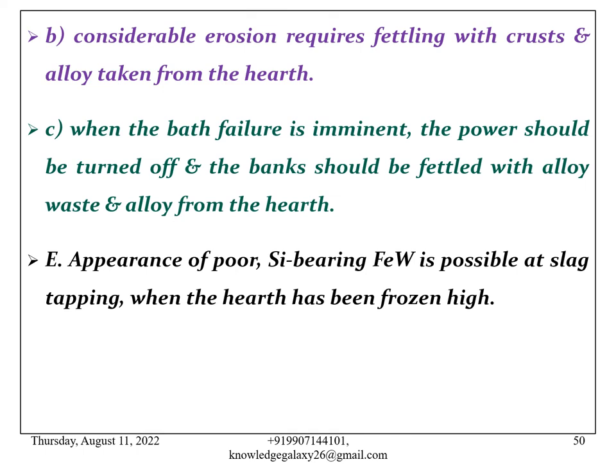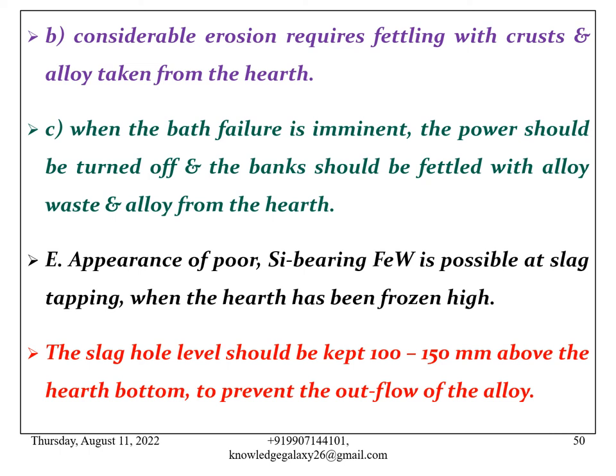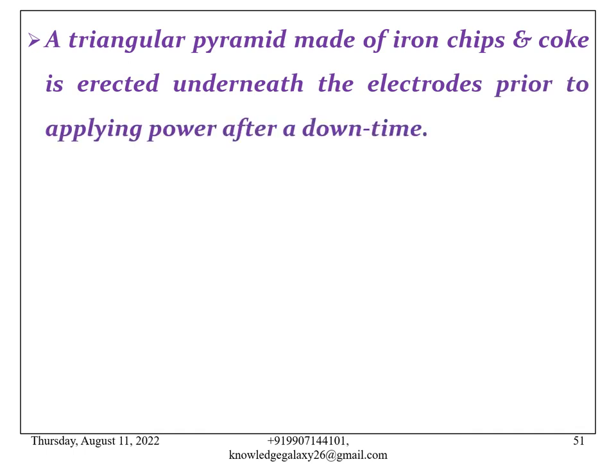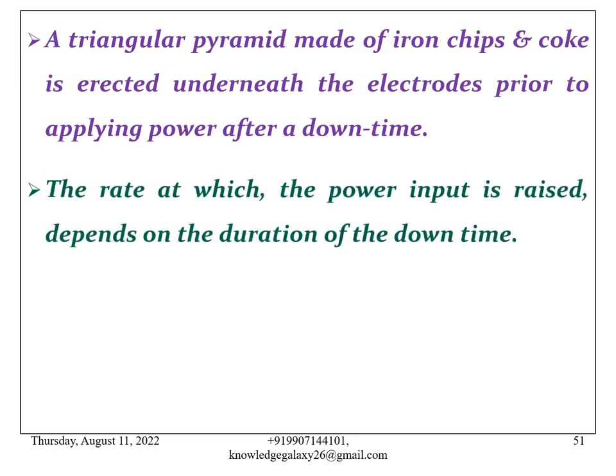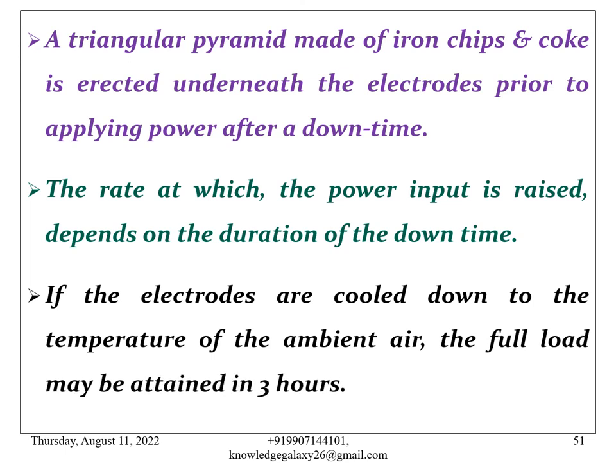Next abnormal condition is the appearance of poor silicon bearing ferrotungsten, which is possible at slag tapping when the hearth has been frozen high. The slag hole level should be kept 100 to 150 mm above the hearth bottom to prevent the outflow of the alloy. A triangular pyramid made of iron chips and coke is erected underneath the electrodes prior to applying power after a downtime. The rate at which the power input is raised depends on the duration of the downtime. If the electrodes are cooled down to the temperature of the ambient air, the full load may be attained in 3 hours.